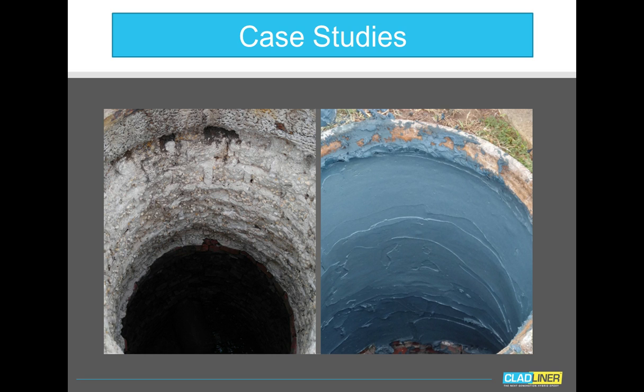So if we look at the picture on the left, obviously we have a traditional brick manhole. You can barely see the bricks because the hydrogen sulfide has resulted in so much corrosion that we have all this corroded, powdery concrete and cement that's sitting on the surface.